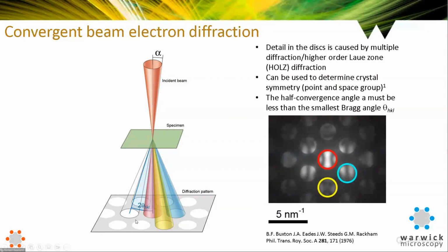So when you look at a convergent beam electron diffraction pattern, what you see is a set of disks. You have a direct beam disk, a circular disk, and then you also have each disk corresponding to different diffracted beams. Now, when you start looking inside these disks, you see these variations in intensity. These are dynamical diffraction effects, and these are due to multiple scattering. These have been known for a very long time. The symmetry of the patterns was worked out in the 1970s.